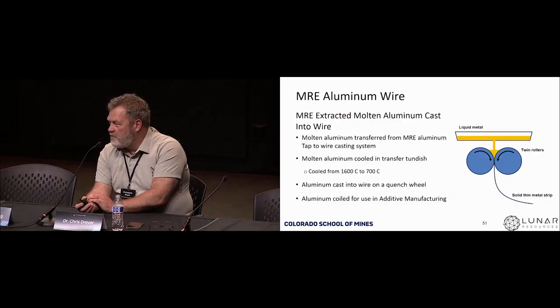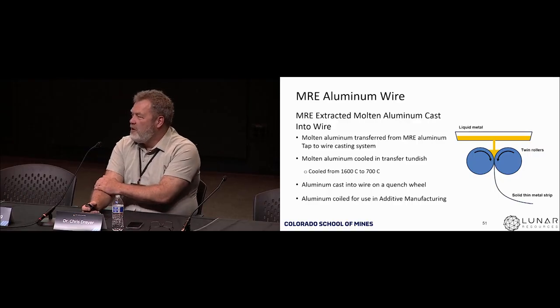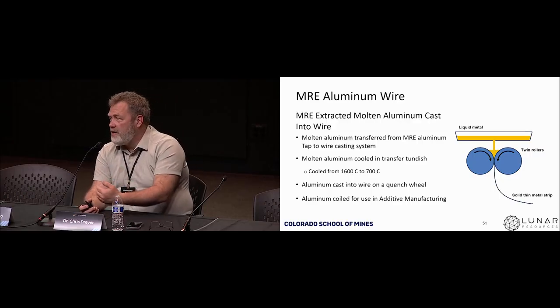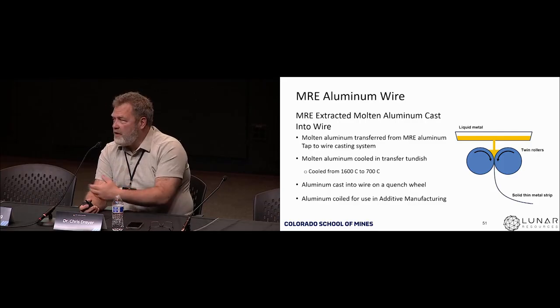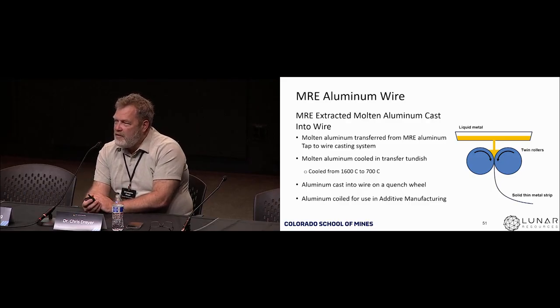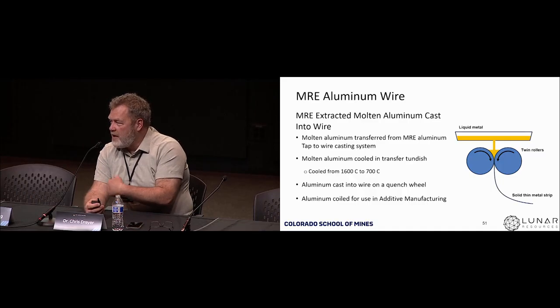And we're getting close to the end. The aluminum wire is actually produced here by a quench wheel. This is one design of a typical quench wheel. Lunar Resources is producing that, so the Mines tap delivers molten aluminum to this. The temperature of the molten aluminum must be dropped from the reactor temperature down to just above its melting point, and then the wire will be pulled off.